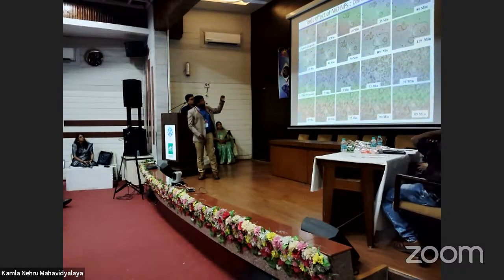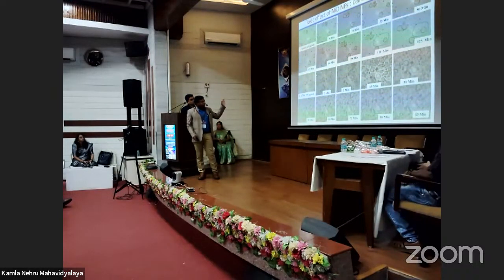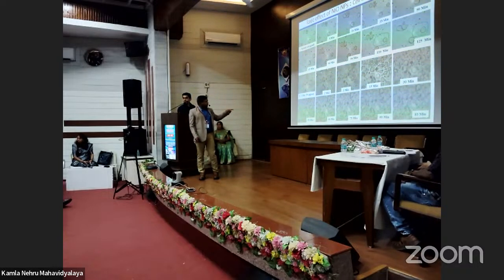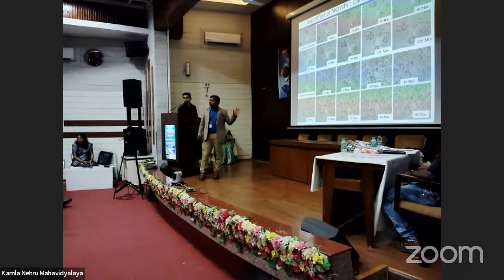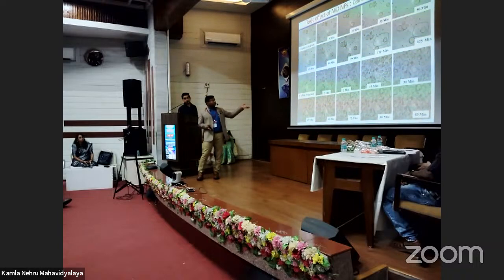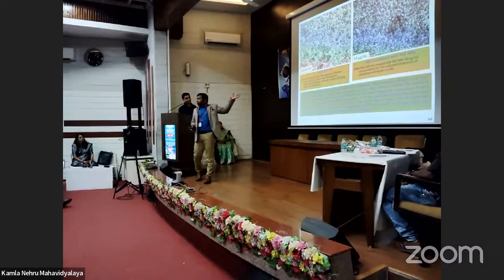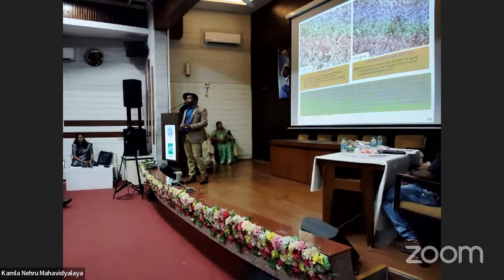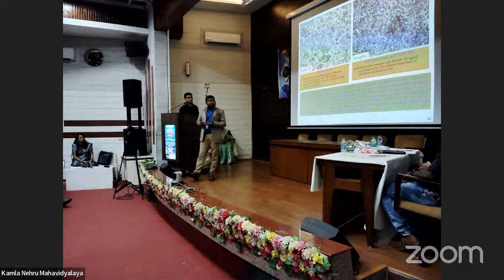assessed on the cancer cell line. You will find the study at 10 microgram at 5 minutes, 20 minutes, 30 minutes, 50 minutes. There will be cracking, and that is the lethal effect, the breaking of the cell. So there is a lethal effect shown, and if you look at 60 minutes, the cells are totally cracked. That means cells are damaged. And next, once the concentration is increased, the cell is totally damaged. So the lethal effect is greatly increased.